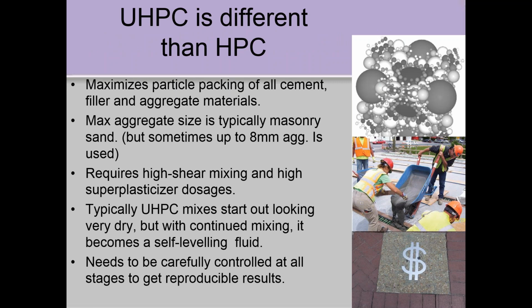And so it's different than other concrete. It involves particle packing. All the materials, including the cement, the fillers, and the fine aggregate materials are particle packed. The maximum aggregate size is typically masonry sand. Now there are some with up to 8 millimeter aggregate, but typically we're looking at minus 3 millimeter, that sort of size aggregate. And you're optimizing the packing down to the nanometer level with these ultra-fine powders, silica fume, and even finer fillers. And it requires a lot of heavy mixing to get it to go. And it shows them pouring it out of a bucket there, a wheelbarrow. We need high intensity mixing, high shear mixing, high superplasticizer doses.